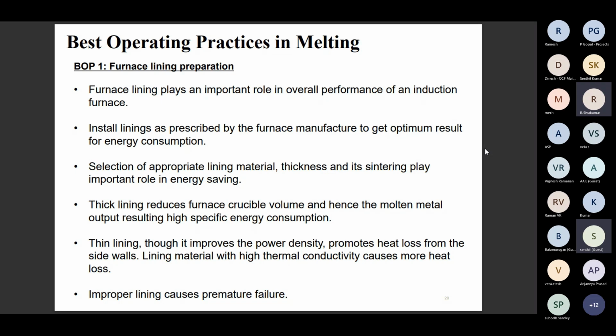The next one is thin lining. Though it improves the power density, it promotes heat losses from the sidewall, with lining material of high thermal conductivity causing more heat loss, and improper lining causes premature failure. So it is very important. A thinner lining is also dangerous, and a thick lining also leads to more energy consumption. We have to optimize the lining thickness.